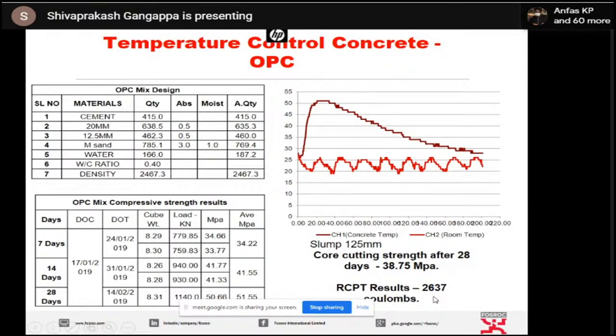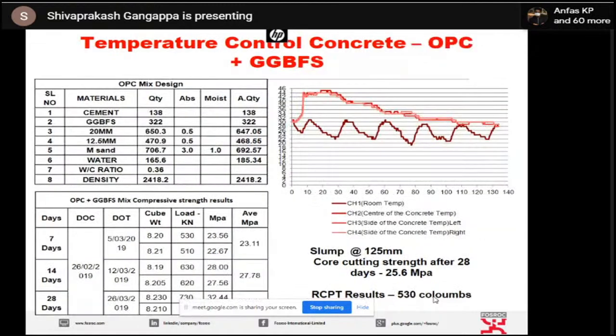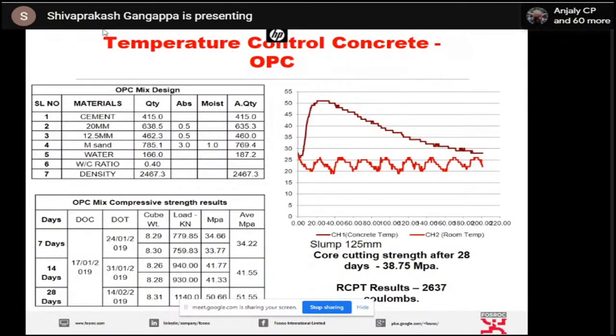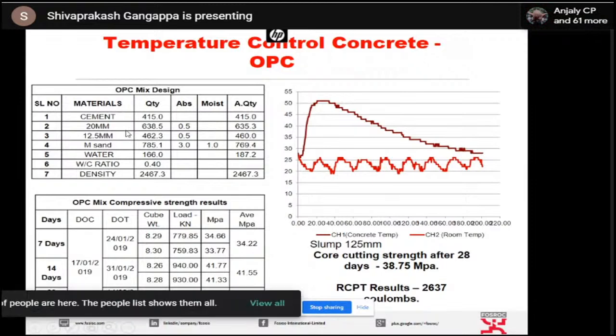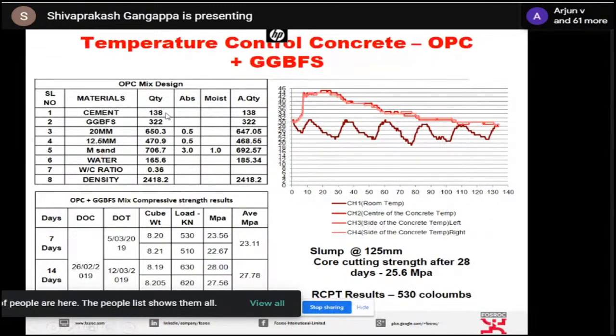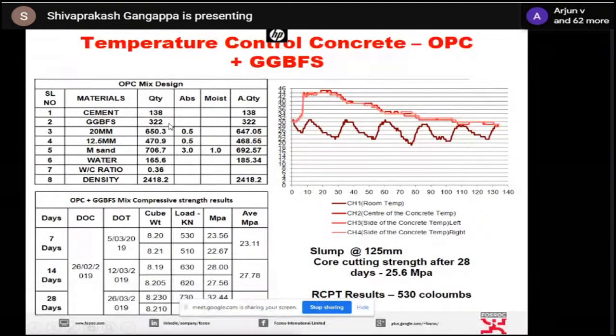And we have done an RCPT value also. The disadvantage of RCPT when you go with 100% OPC is that it is very high. The moment you shift this with a secondary cementitious material, for example, you can see this mix, a high volume replacement of GGBFS. Whatever the 400 kg, 415 kg we used in the first test, in the second test we are using only 138 kg cement, and the balance is replaced by GGBFS. Because of this, the peak rise in temperature could go only up to 44 degrees.